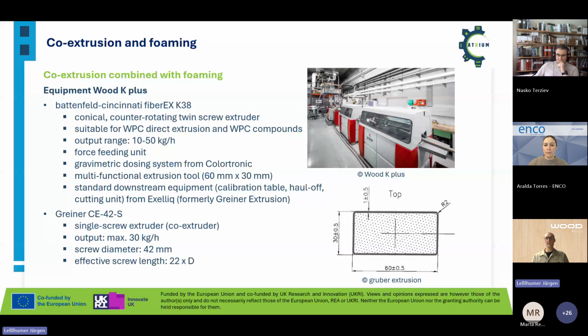And this is the equipment we use. For the core layer, with the recycled and bio-based material, we use a conical counter-rotating twin screw extruder from Battenfeld Cincinnati. And for the shell layer, we have a single screw extruder from Greiner.